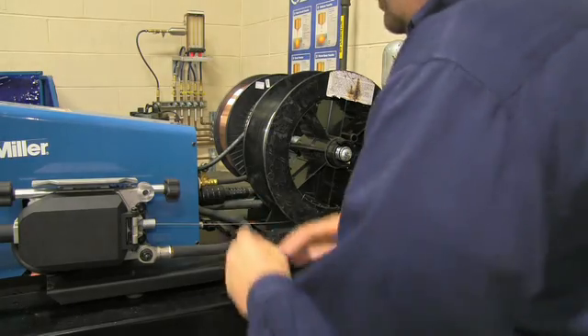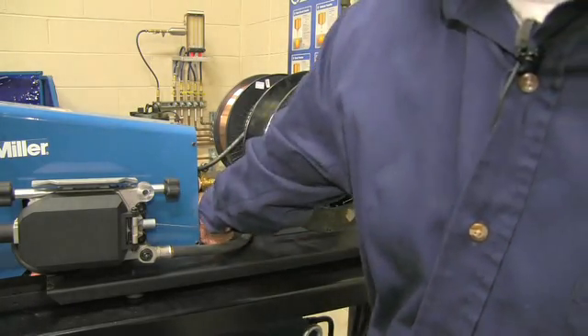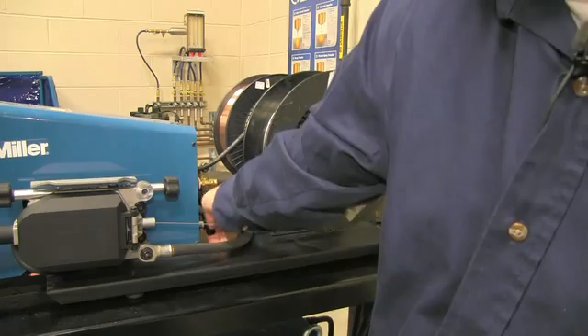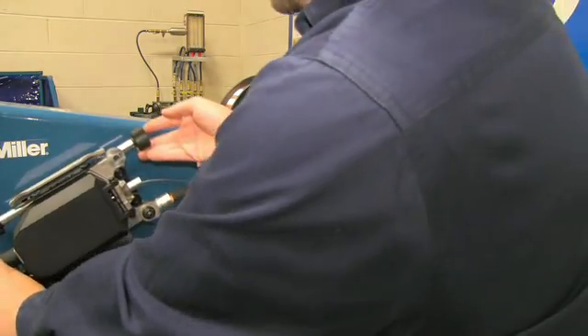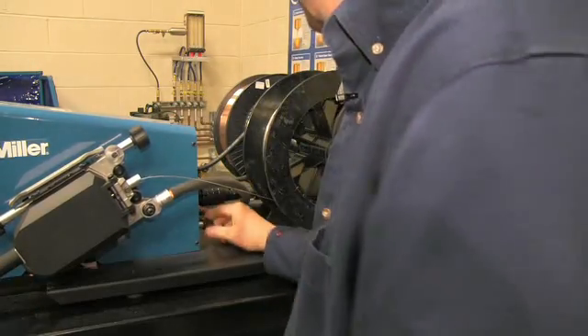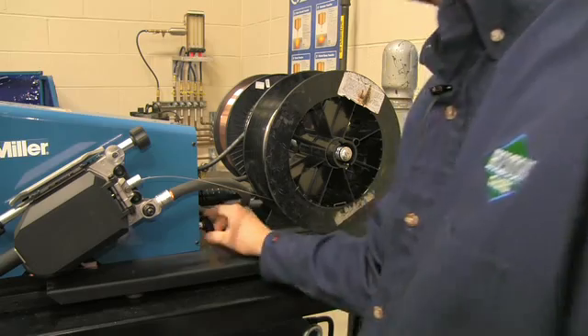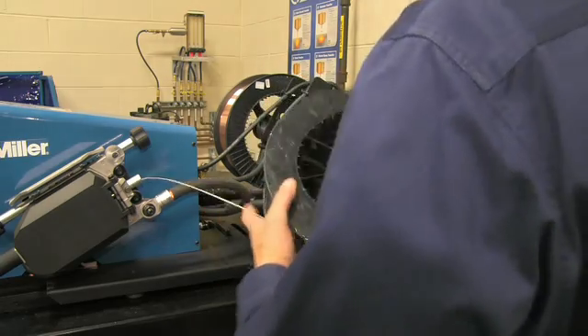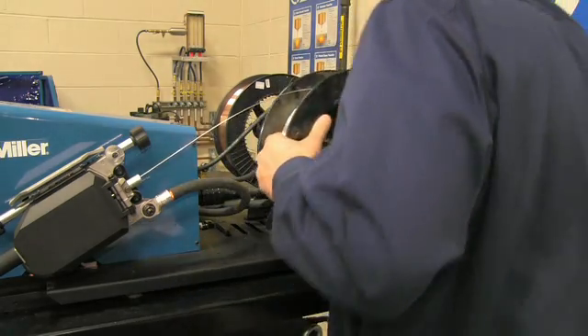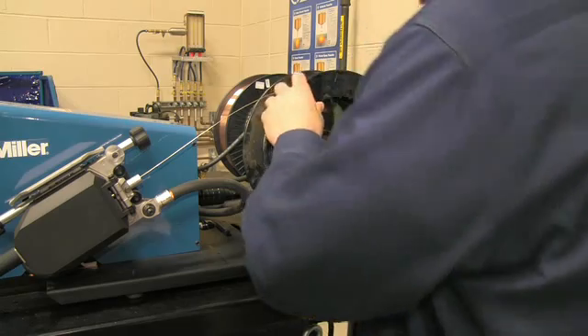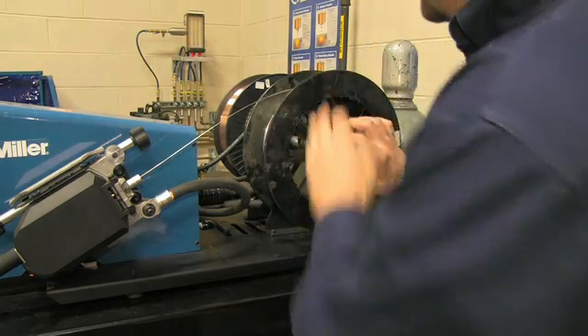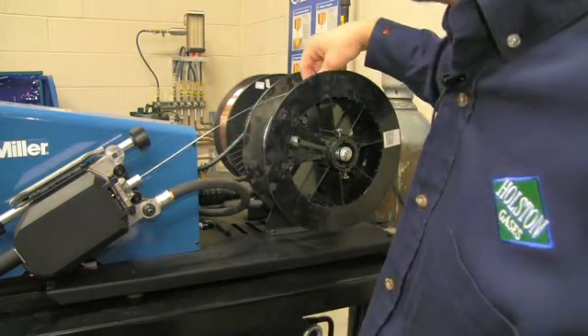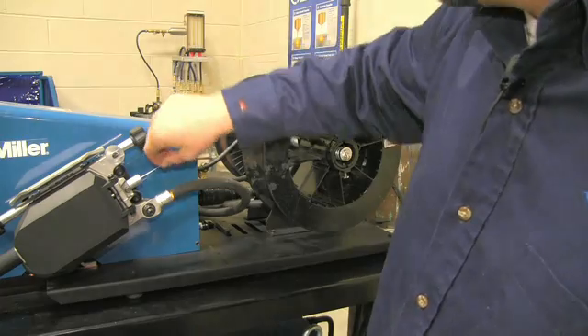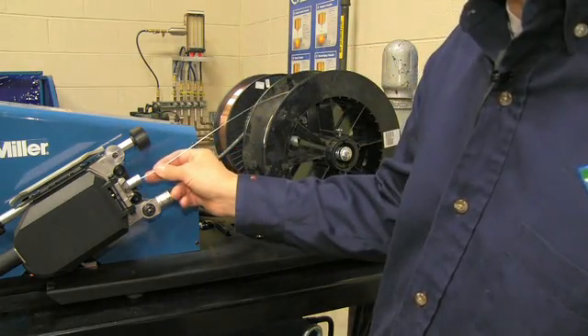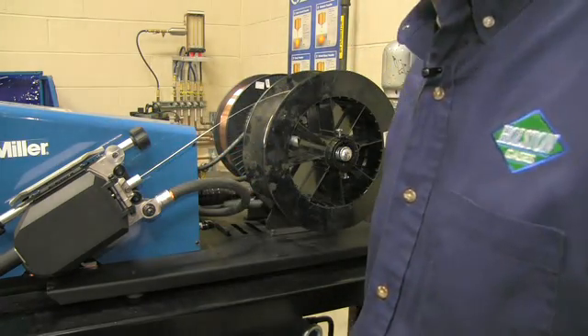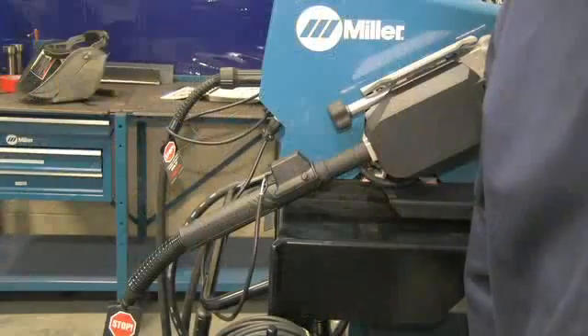Now also, with some of the newer feeders, there's a tension knob in the back of the wire feeder, and so we can position this at 45 degrees, tighten it down, and then now we can install our spool where the wire comes off at about 45 degrees. And this would be ideal right here. This would allow for the wire to come off the spool and then to go into the inlet guide in a straight line, so there's as minimal wear on the inlet guide as possible.